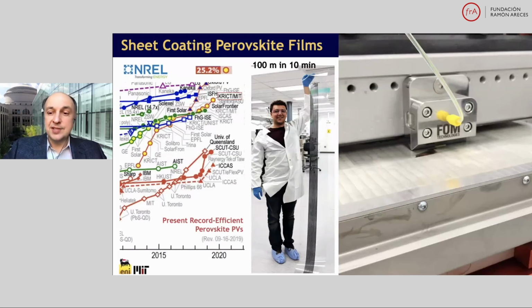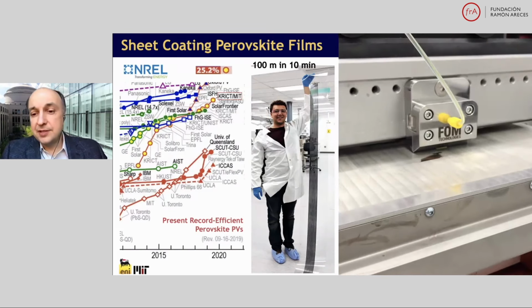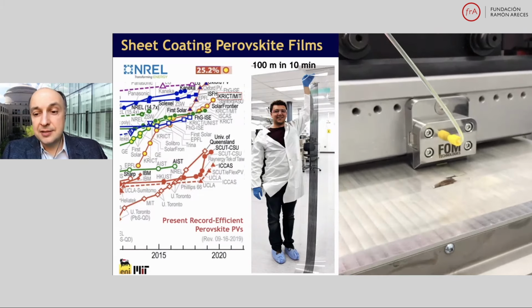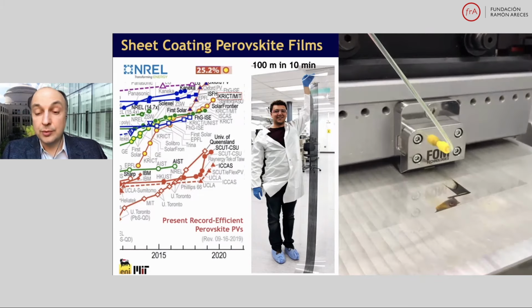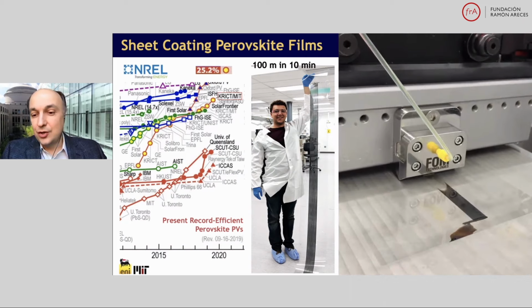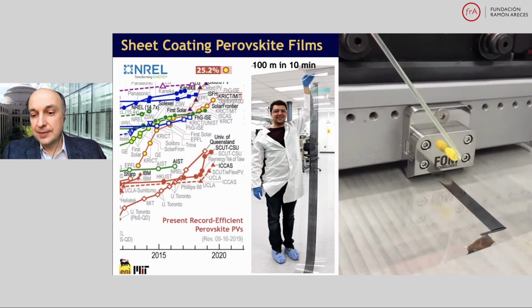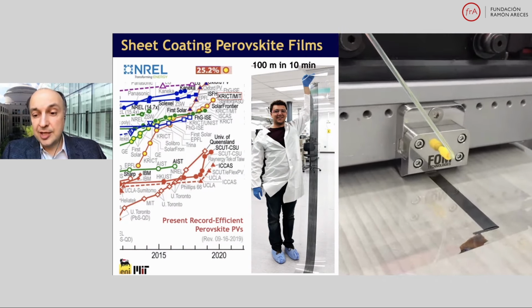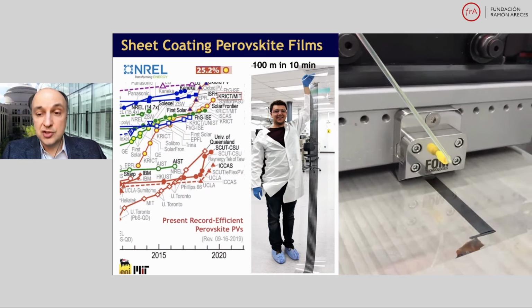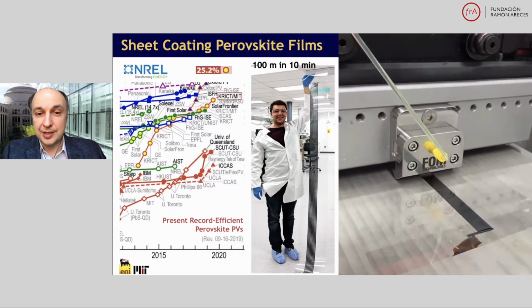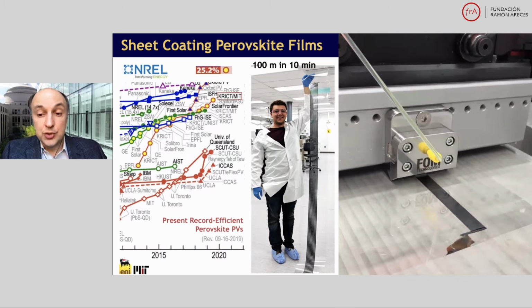Here's an example. This is a video of a perovskite thin film being slot die printed on this particular piece of plastic. It starts as a transparent liquid that then solidifies into a dark solid that will be very efficient at absorbing light. Solutions of these materials we have perfected. We can now coat, over 10 minutes, a 100-meter long roll of this material, if that's what we wish to do.